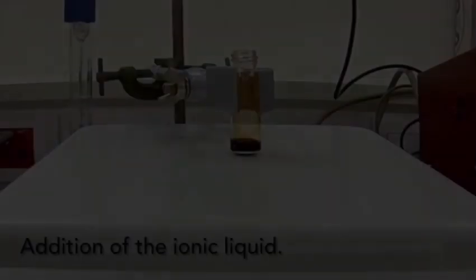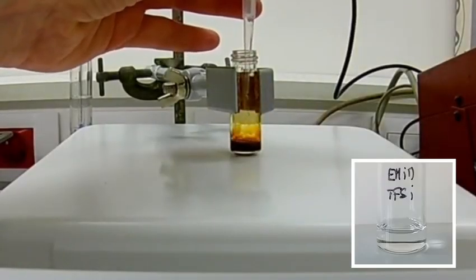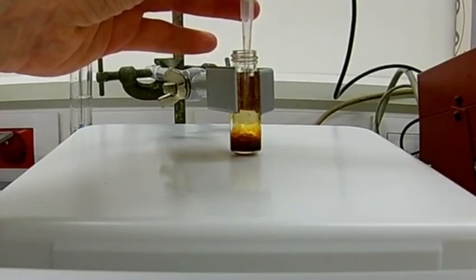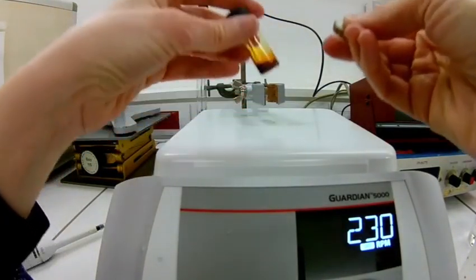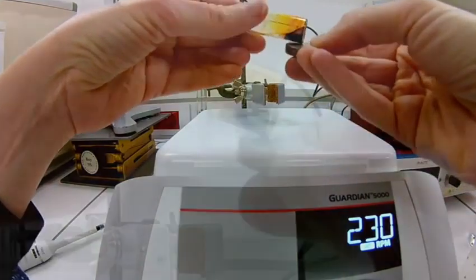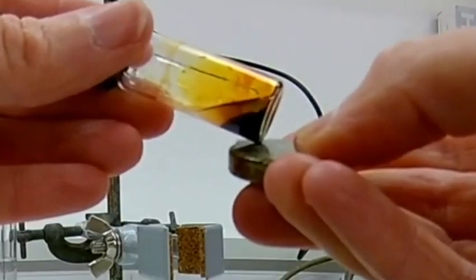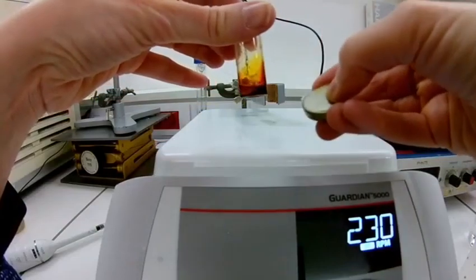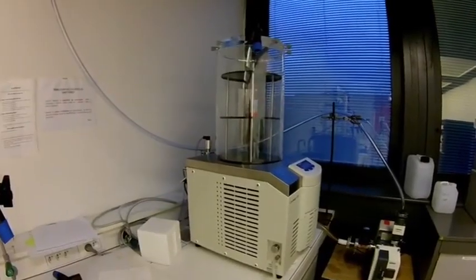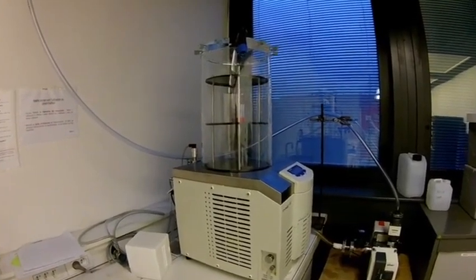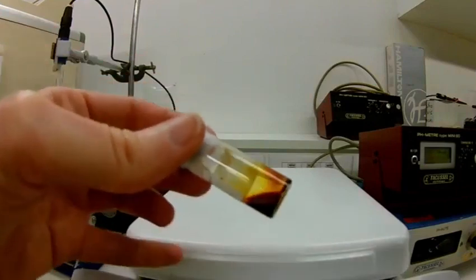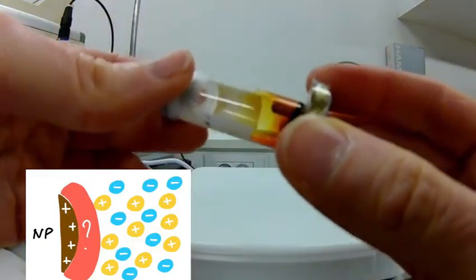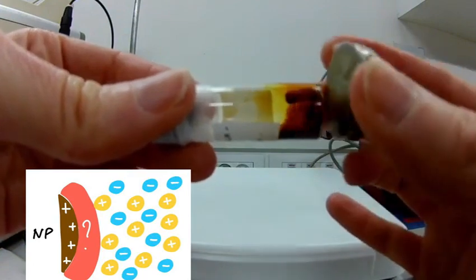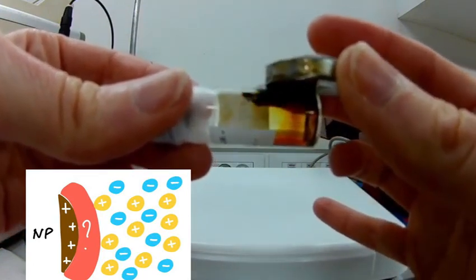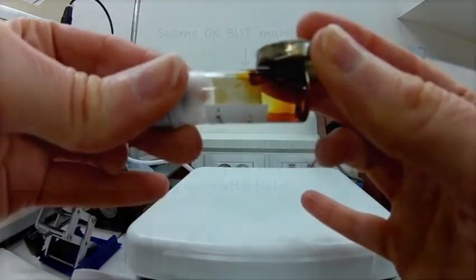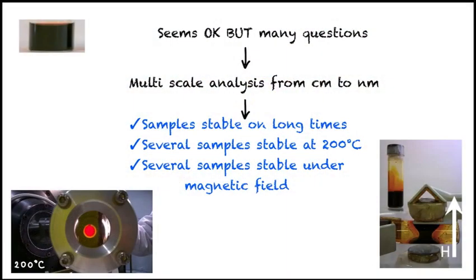Once the interface is tuned, the ionic liquid is added. You see the drops of the transparent liquid. After a stirring time, in this case, it appears that the particles moved from the aqueous phase at the top to the ionic liquid denser phase at the bottom, both liquids being immiscible in the present example. Whatever happens at this stage, the next step is to remove water by pumping. At the end, we recover the dry ionic liquid only, which is now the solvent. In this example, the liquid seems homogeneous by eye and follows the magnet. So it seems okay, but there are many questions.